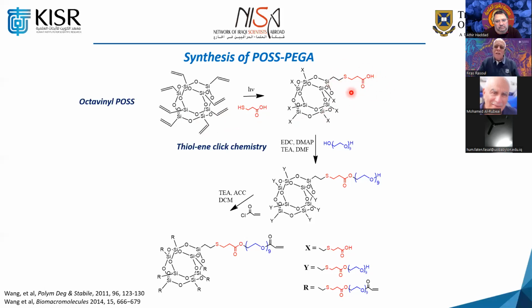So you will introduce this acid group into the POSS molecule. And then, of course, we tried to extend it by putting polyethylene glycols. You will be able to use a different type of polyethylene glycol. In our case, we use 9 repeated units of ethylene oxide groups, which is a molecular weight of about 400, but you will be able to go much higher as you wish. So we hooked this one through a simple chemistry into that POSS.